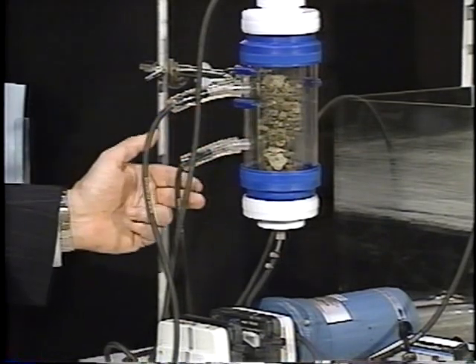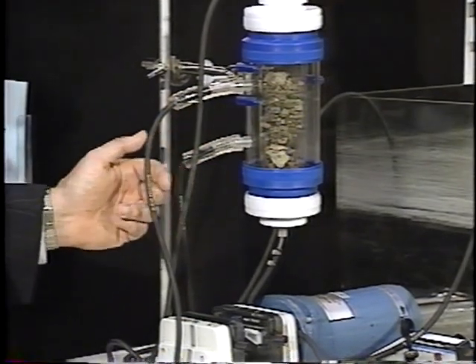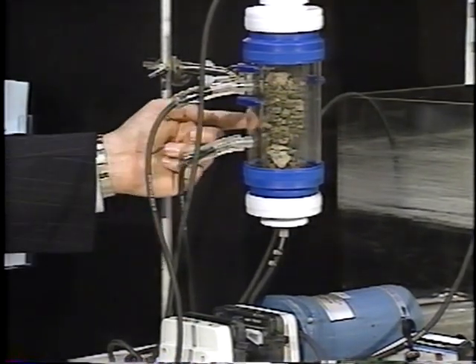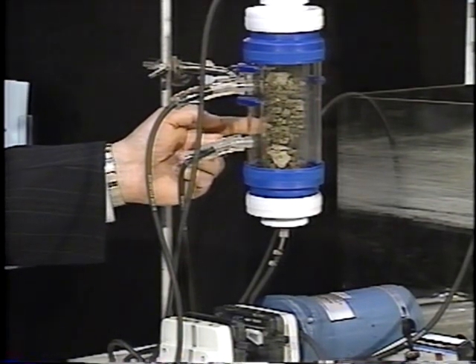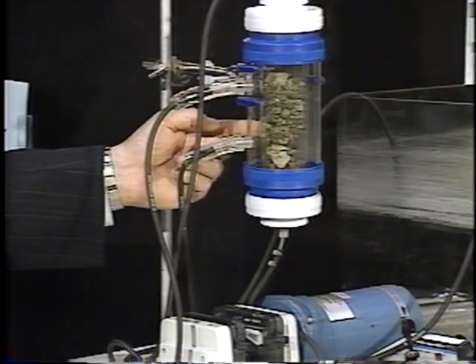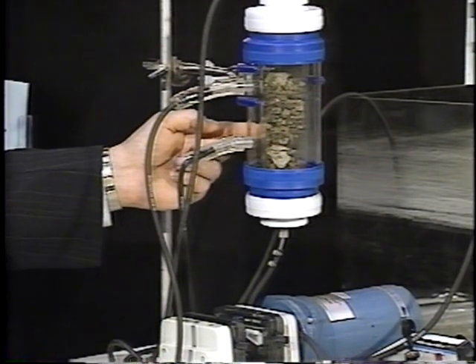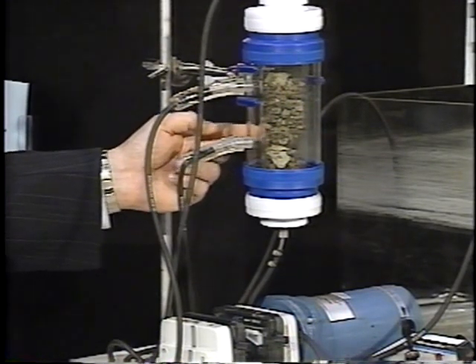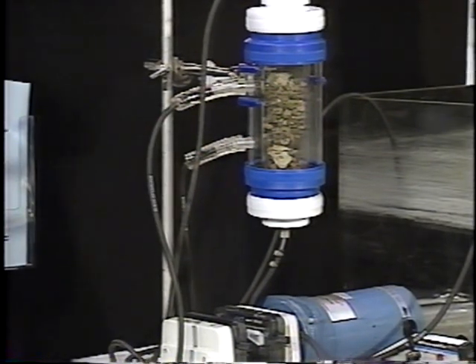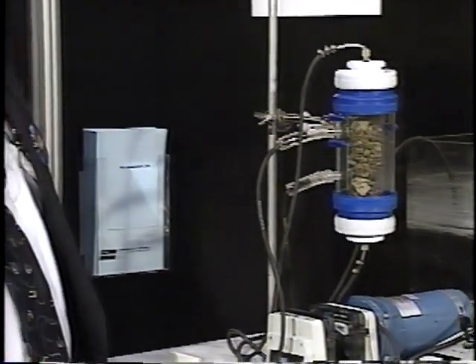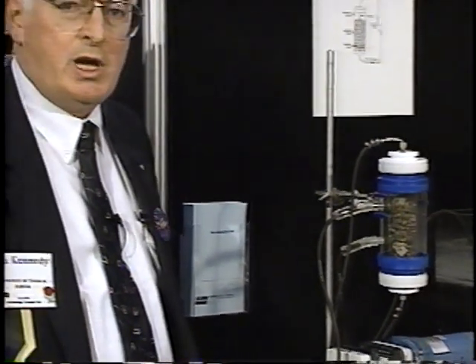We then add water to the system and repeat the process, and as water passes through, this asphalt would be removed from the aggregate surface, leaving a net amount of asphalt. If a large amount of asphalt has been removed, then the material probably is not compatible and that source of aggregate might be eliminated. If we find that a large amount of the asphalt still remains, then that shows a compatibility between the two materials and provides some acceptance.